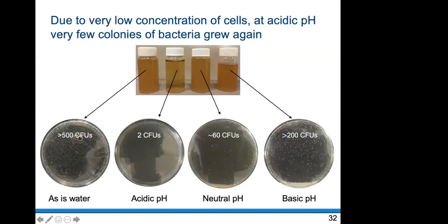But at acidic conditions, I have only 2 colonies. At neutral conditions, about 60 colonies, and at basic conditions, over 200 colonies. So it shows that it is not the pH, but the sponge that is helping to remove these bacteria and preventing them from regrowing into full-fledged, big colonies like this.